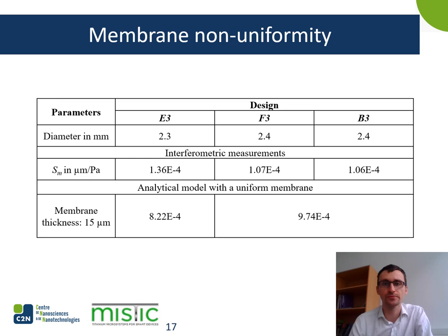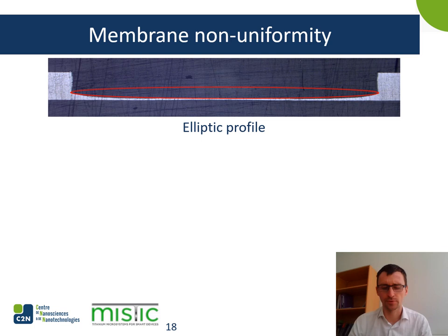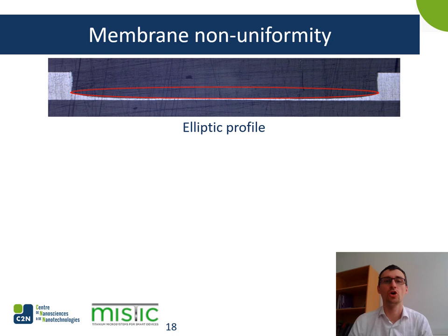In this table we report the results for the different diameters tested. The interferometric measurements are compared with analytical theory, and there is a factor of 4 to 8 between analytical theory and what we obtained for our membranes. We supposed, as with the embossed membranes, that we could explain the difference by the bottom edge profile. When looking closely, we noticed that we could model the membrane thickness profile by an elliptic shape. So we implemented finite element modeling analysis considering this new shape. We also performed the same kind of model for the embossed membrane and obtained good results.